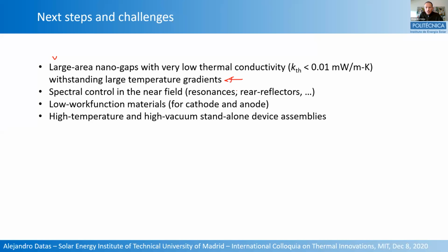In thermionics, typically, they need a bit larger gap distances of typically greater than 1 micron. But there is an interest in reducing this distance to get more power, and then you have, in the thermionic side, a problem with the near field radiation. So the idea is that having this hybrid concept, you can make good use of these photons that otherwise were wasted.